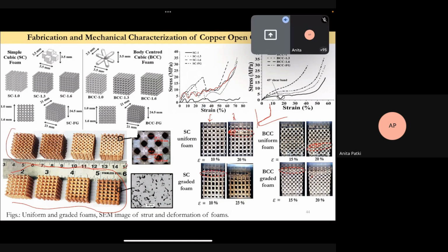Okay, but copper is a ductile material; it should not fracture. Okay, so there is still some, because the density is not 100%. There are micro porosities, as I mentioned, in the density, which gives the fracture when you put a load at 90 degrees.